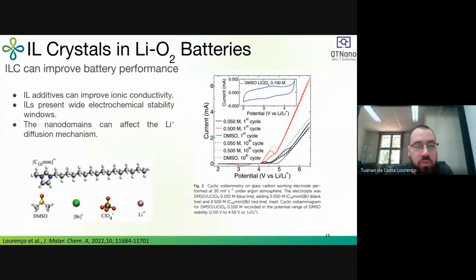And here, the goal of this project was to understand what happened with the DMSO lithium perchlorate electrolyte in a lithium-oxygen battery when we add this ionic liquid crystal here. The cation of the ionic liquid is this imidazolium with 16 carbons in the chain, and the bromide anion. So an ionic liquid crystal is an ionic liquid that can create some kind of nanodomains in the structure. If we look here at the cation, we have positive charge in the ring, and we have an apolar chain here. So that means that in the liquid, this apolar chain is going to interact with other apolar chains. And also here, the rings are going to interact with the anions because of the Coulombic interactions, but also with the other rings that will be closer because of the interactions between the apolar chains. So we can create this kind of nanodomains within the liquid. And of course, if we are changing the solvation shell of the ions, we are changing the properties.